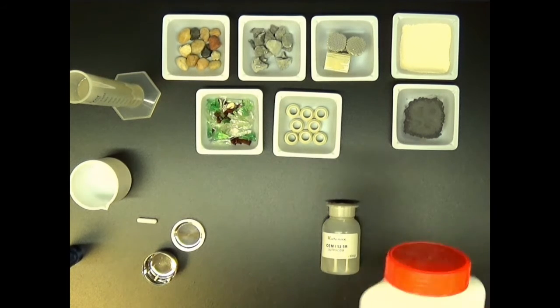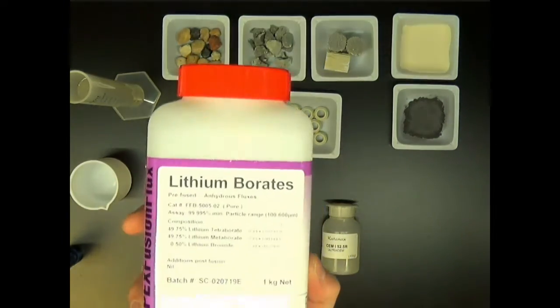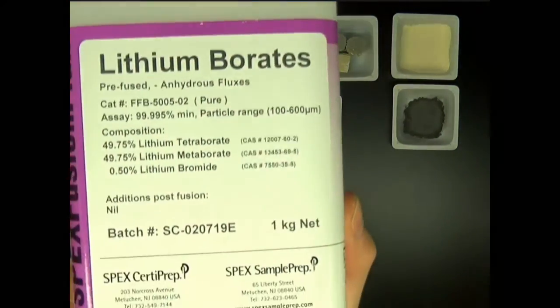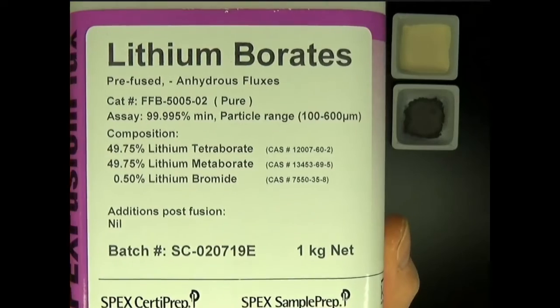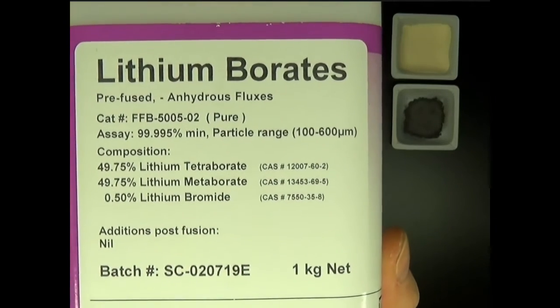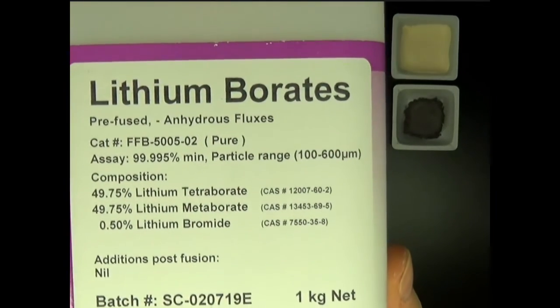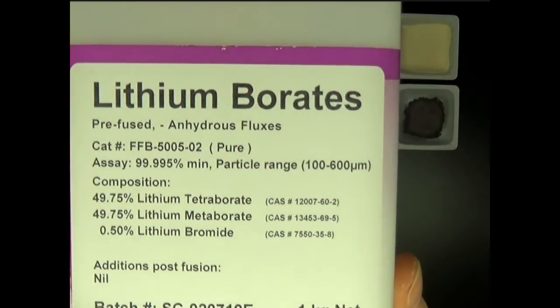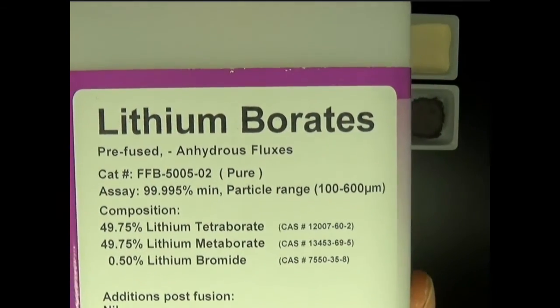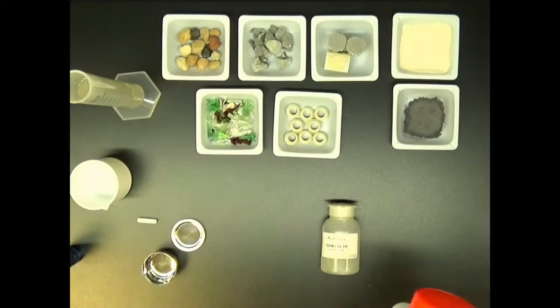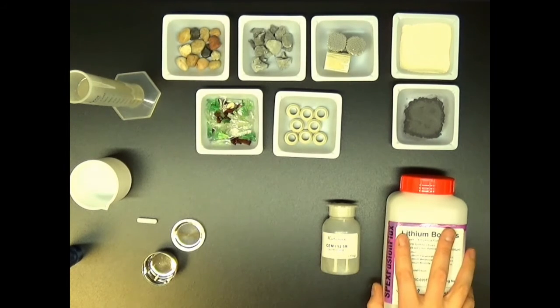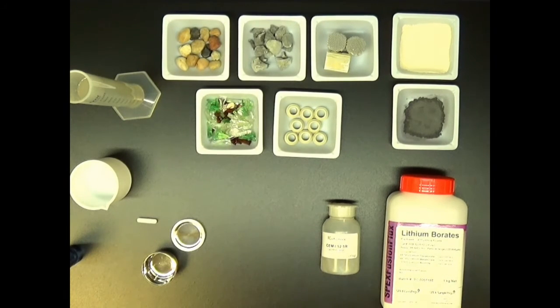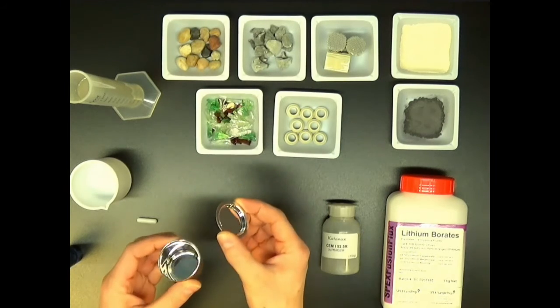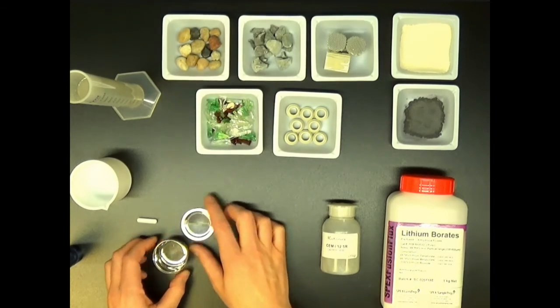The final aspect I want to discuss is related to the flux itself. We have an example here of 50-50 lithium tetraborate, lithium metaborate flux. We have a little proportion of lithium bromide in this one as a non-wetting agent. A non-wetting agent will help to release and avoid sticking of the fusion mixture.